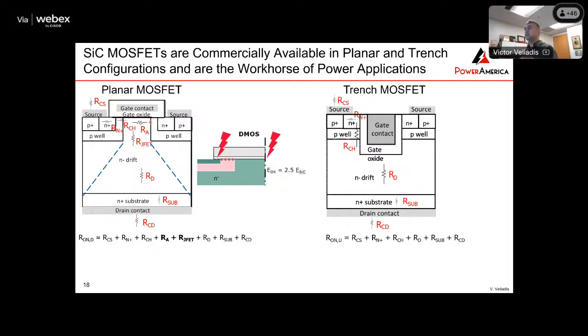So low resistance because you don't have the JFET, and also the fact that it's a smaller device. It so happens that the mobility in silicon carbide is anisotropic, and the vertical mobility here, so having a vertical channel, the mobility is 20% higher. The problem, of course, with the trench MOSFET, because nothing in life is free, is that it has these areas